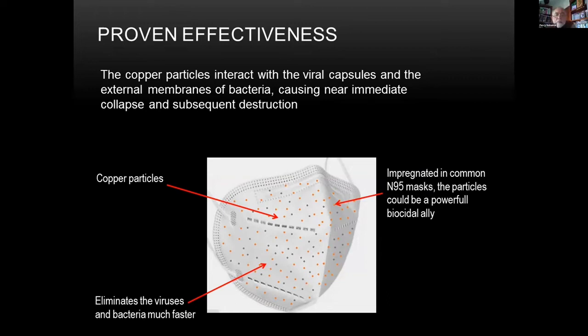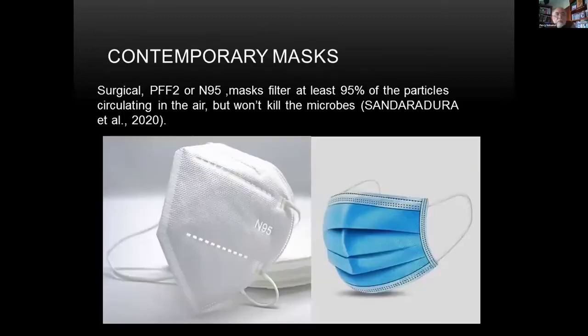Thus, as technologies such as electron microscopy are applied in experiments involving copper as a sterilizing agent, its effectiveness is proven through the degradation of the glycoprotein membrane of viruses and bacteria when in contact with its ions, consequently destroying them. Well, the contemporary masks, such as the surgical, PFF2 or N95, despite filtering at least 95% of the particles circulating in the air, do not eliminate the viruses and bacteria, which can survive up to 3 days impregnated in the fabric. However, we need copper to purge these microorganisms from masks, thus lowering the risk of infection.